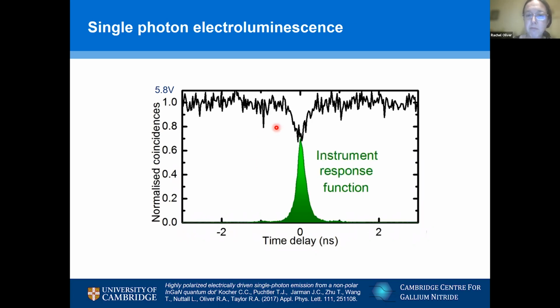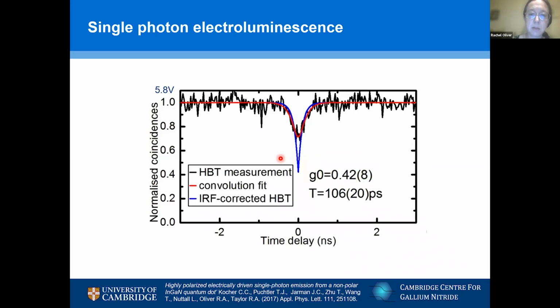I'm zooming in now around the dip. And what we can add into this diagram is the instrument response function of the detector we're using to measure this dip. And you can see that it's actually got almost the same width as the dip we're seeing. So this data is hugely affected by the inability of our detector to really keep up with these very fast emitting quantum dots. If we deconvolve the impact of the detector from our data, we actually see that we'd estimate the dip to be down to about 0.4. And we can also use the same data, same fit, to estimate the lifetime of the dots here as being about 100 picoseconds. So by nitride standards, really very speedy emitters.